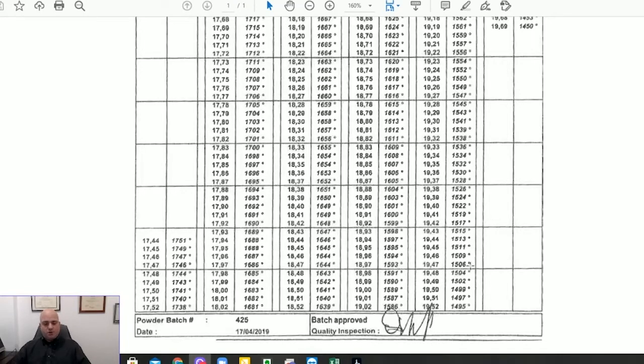So if you set your zirconia at 1480, and the true reading is truly at 1506, you can imagine that that's 26 degrees hotter than what you really intended to sinter your zirconia with, which will absolutely affect your end results, or your aesthetic results, for those crowns. By doing so, you're then able to adjust your sintering temperatures by reducing it by 26 degrees, because from 1480 to 1506 is 26 degrees. And then the next cycle you run is at 26 degrees less than 1480.